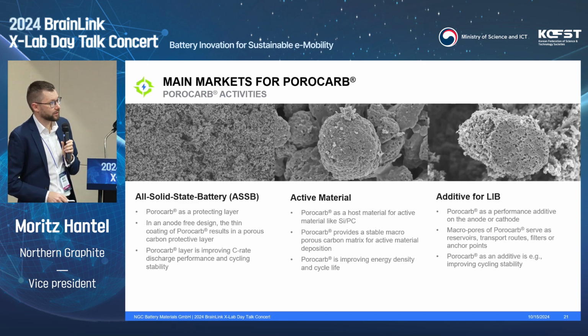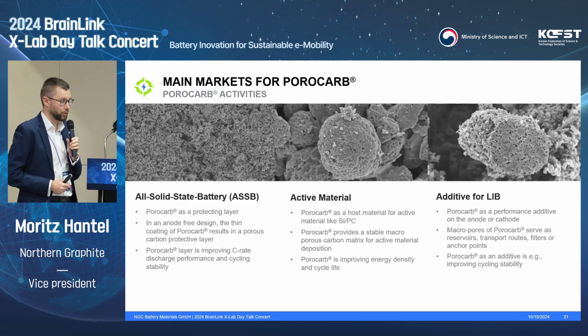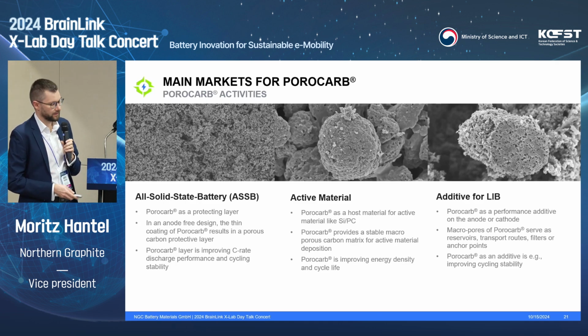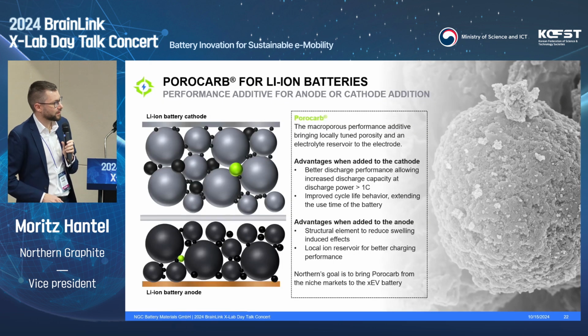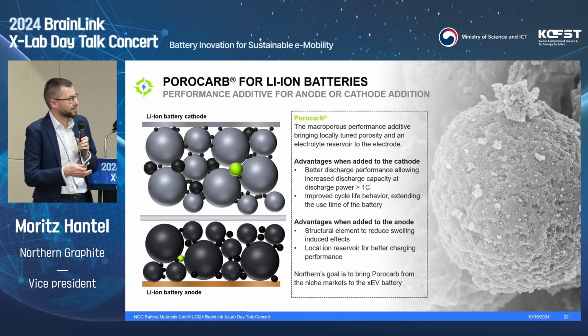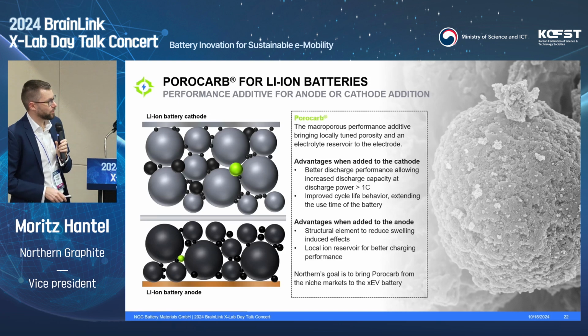And then for sure also the classic additive for LIB, and I can also add here SIB, because in the end it's for liquid electrolytes, where porocarb, due to the porous structure, aids as a performance additive because it enhances the ionic conductivity and not necessarily the electronic conductivity, because the focus here is really porosity, enhancing the porosity and the ionic conductivity. So, just two examples to show how it can be used, with different advantages depending on where you apply porocarb.